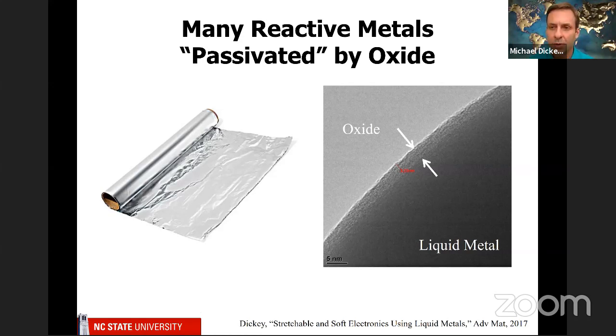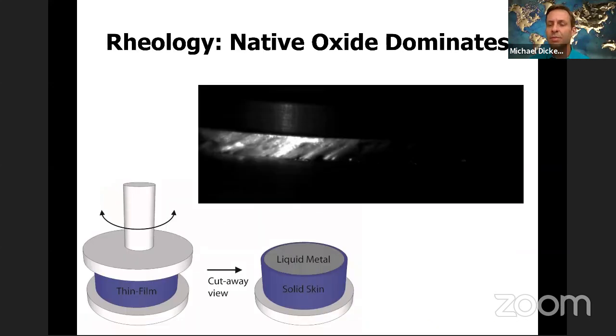Okay, so why is this a big deal? And this is going to be probably the most mechanics part of my talk. And that is to talk about the rheology, the way that this stuff flows. So we've studied this in a number of ways, one of which is shown in this cartoon. So we have a bottom plate shown here, a top plate, and then we put the liquid metal in between. And if you do a cutaway view, what you're really measuring is the mechanics of this solid-like oxide skin that's 3 nanometers thick, because the bulk viscosity is like water. So in terms of the rheometer, it's almost like it's not there.